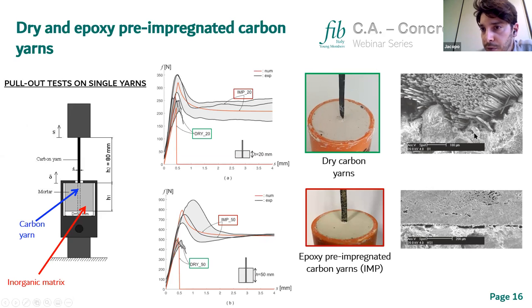Here we can also see from the same images the bond between the dry yarn and the mortar. The inner filaments can slip while only a few filaments are bonded to the mortar. While in the case of coated yarn, we have delamination at the interface between the yarn and the mortar. However, the frictional forces that develop at the interface are quite high, and so we have this plateau on the curve.